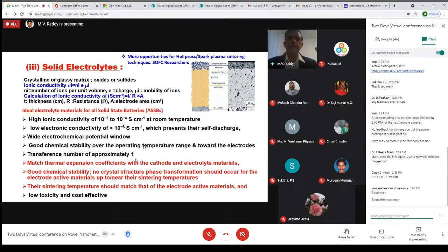Again, solid electrolytes. In fact, recently there is a problem with safety issues because of flammability. Is there any way to reduce, for example, the interface and flame safety issues by using solids? It means that instead of the liquid electrolyte, we use an inorganic solid electrolyte. The advantage of this technique is that we press the cell in layers by compacting.